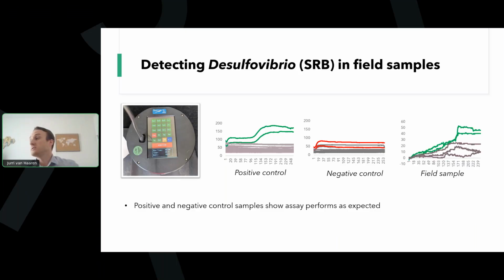The next step was to test field samples. We collected several field samples and tested 5 of them. Out of the 5 samples, 4 turned up negative, showing there are no Desulfovibrio microbes in those samples. One sample turned up positive, showing that Desulfovibrio is present. You can see the curves here. They look a little more messy compared to the control, just because there are other materials from those field samples that interfere with the fluorescence a little, but it works just as well. The device did show up positive.